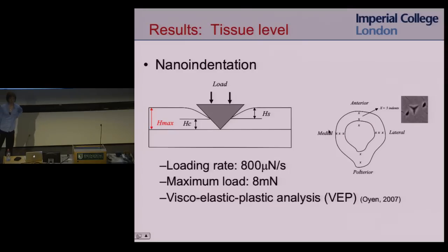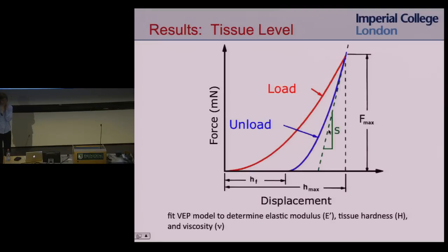We measured the mineral using nano indentation. So very similar to a low deflection curve, you get a similar type of curve. You indent it with a little point. Here's what an indentation point looks like. We did this in different regions of the bone in cross-section, and used a viscoelastic plastic analysis. We did this in collaboration with Michelle Oyen, who's at Cambridge. Here's a typical nano indentation curve.